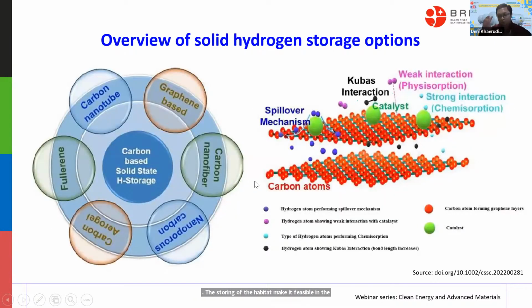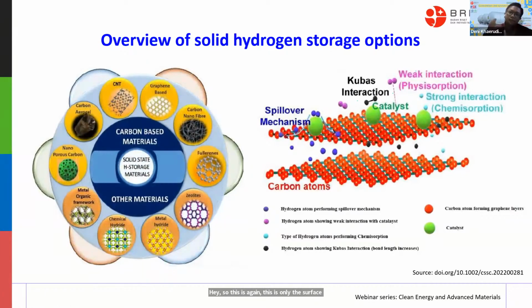Okay, again, this is just to give some perspective on what kind of carbon-based solid hydrogen storage we can use, like CNT, graphene-based, carbon nanofiber, nanoporous carbon, carbon aerogel, fullerene, and many others. So many. And this is the interaction, the weak interaction on the walls, as I mentioned before. If possible, you can also put in some catalyst, but only a few. Maybe if we use some catalyst, it will enhance more. I will show you some with catalyst and without catalyst. So this is only the surface interaction of the hydrogen and the carbon. This is the carbon-based material that we can use for hydrogen storage.